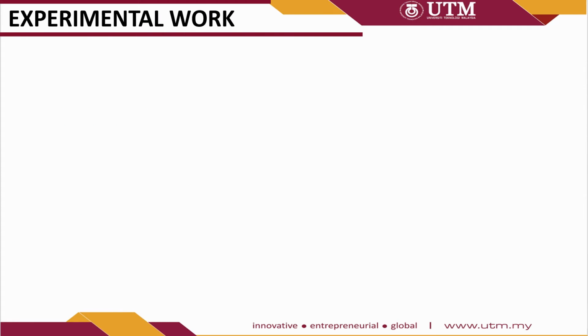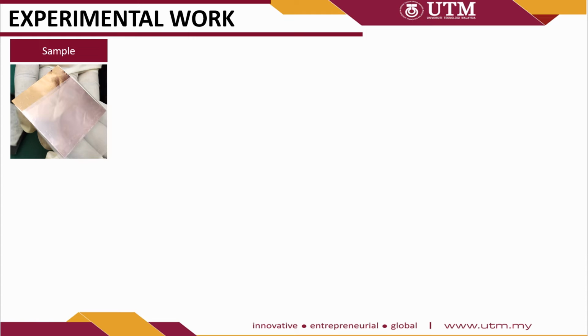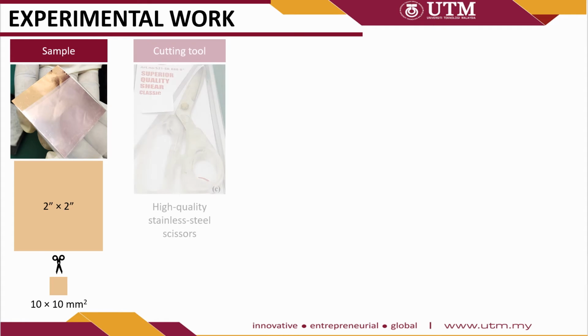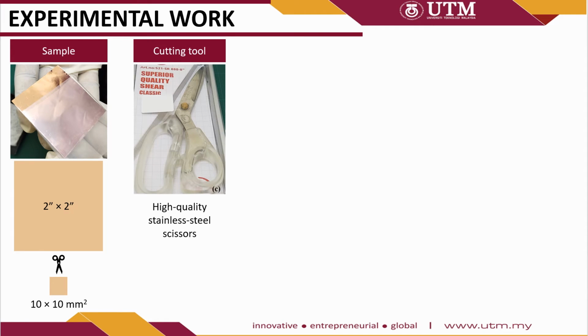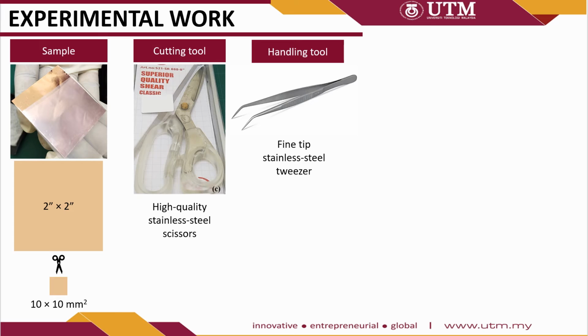For experimental work, copper foil substrate grown with single-layer graphene in the original size of 2 x 2 inch was cut into small size samples by using a pair of high-quality stainless steel scissors. A fine-tip stainless steel tweezer was used as a handling tool.